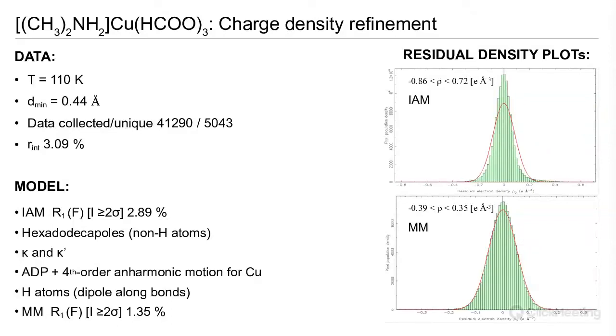But if we look at the residuals, there are two telling things. I'm looking now at the top plot. The width of this is reasonably large and the peak is quite high, but it also doesn't follow the normal distribution that one might expect. So this points towards some discrepancy in the residuals. So we introduced a multipolar model expanded up to the hexadecapoles, at least for every atom other than hydrogen. We refined kappa and kappa prime, the expansion parameters that Piero described, and we find an appreciable drop in the R factor down to 1.35. We see a much tighter distribution of the residuals, which are distributed normally. So we're confident that we've done a good job of the charge density refinement in this case.